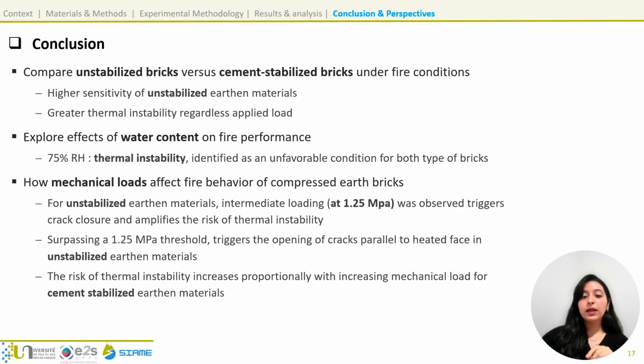And third, looking at the influence of mechanical loads, for unstabilized brick, intermediate loading at 1.25 megapascals closes cracks perpendicular to the heated face, which amplifies thermal instability. When the load exceeds this value, cracks parallel to the heated face open, relieving pore pressure. But for cement-stabilized bricks, thermal instability grows proportionally with increasing load. Overall, these findings highlight the critical interplay of water content, relative humidity, and mechanical stress on the fire behavior of compressed earth bricks.